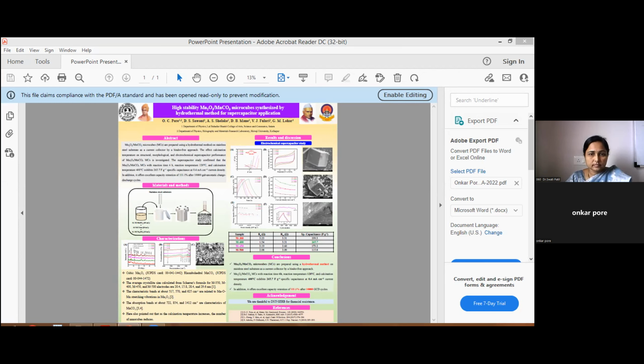Then these are the conclusions. Mn2O3, MnCO3 microcubes are prepared using the hydrothermal method on a stainless steel substrate as a current collector by a binder-free approach. Mn2O3, MnCO3 microcubes with reaction time 6 hours, reaction temperature 120 degrees Celsius, and calcination temperature 400 degrees Celsius exhibited 260 at a given current density. And the optimized sample shows excellent capacity retention, about 111.1% after 10,000 cycles.